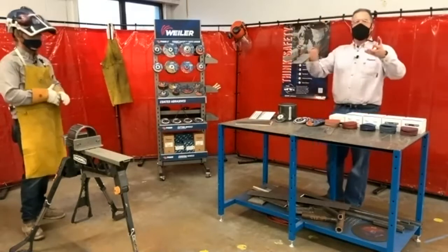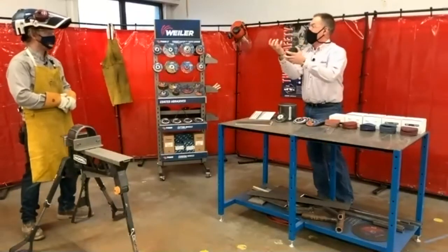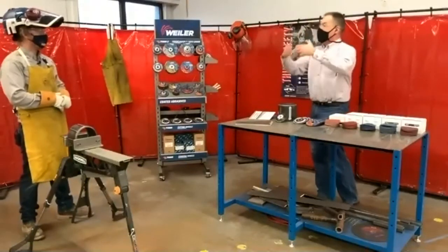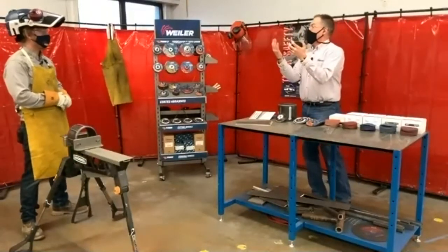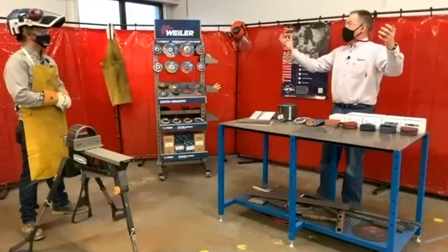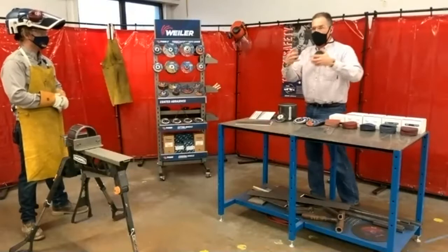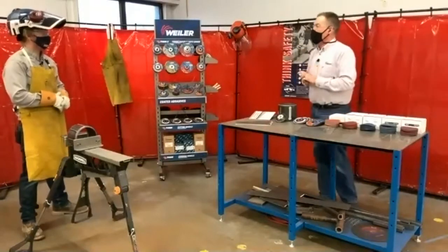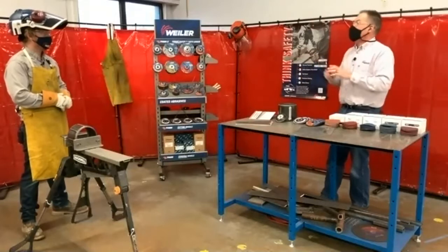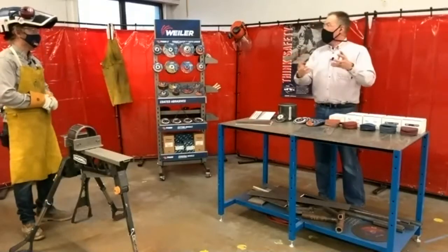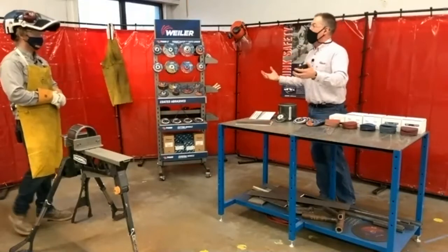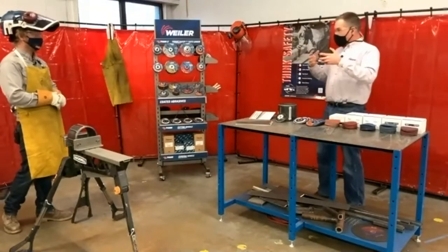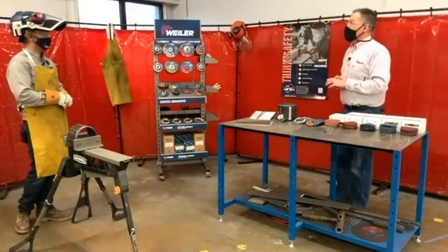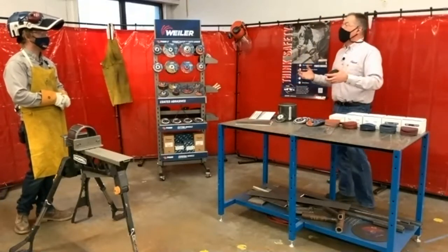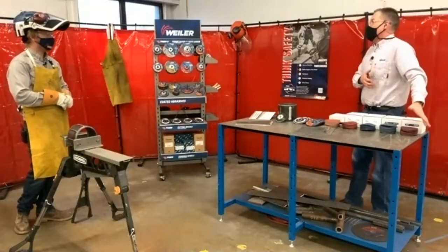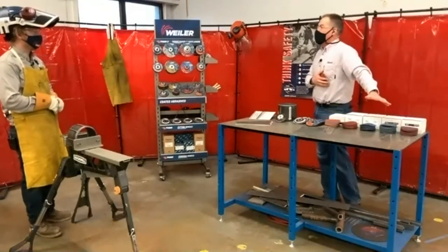100%, right? But ceramic grains and their ability to maintain their edge, just like any cutting tool, right? It's not so much that any abrasive is sharp right out of the box. It's about how well it can actually stay sharp throughout the course of its use. And ceramic grains, certainly under the appropriate conditions and with the necessary accommodations, will absolutely do that. So now you're looking at your high nickel alloys, your armored steels, tool steels, Inconels, titaniums, the materials that are going to be much harder to grind and are really going to take a toll on an aluminum oxide grain and cause that grain to dull at a much faster rate.